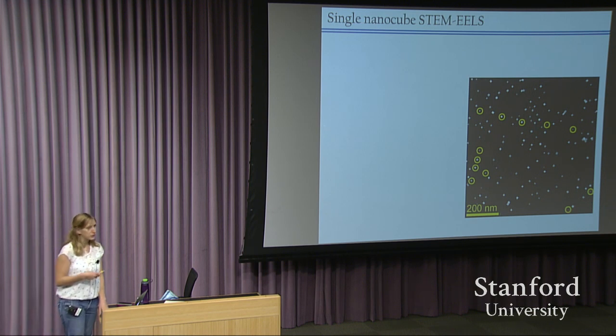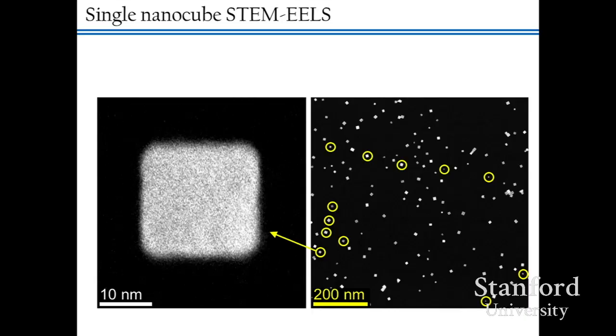And then we switch over to something called scanning transmission electron microscopy mode, where we basically focus the electron beam down a little bit, but we lose a little bit of imaging resolution in order to be able to get higher spectral resolution. So here's one nanoparticle. It's 23 nanometers across. It's palladium.